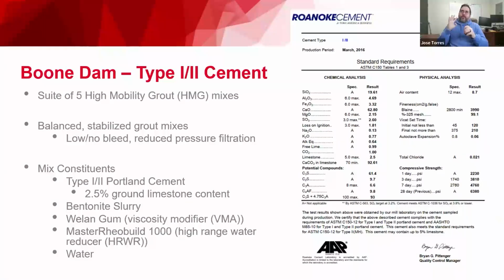So we're going to look at 4 different jobs. The first one was Boone Dam. We used a type 1-2 cement, Portland cement. On that job, we had 5 high mobility grout mixes. These are balanced stabilized grout mixes, meaning little to no bleed and reduced pressure filtration.